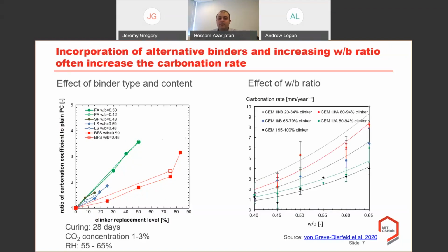The other one is the water to binder ratio, the quantity of the water compared to the quantity of the binder that we have in our mixture. One of the important effects of the carbonation is on the hardened properties of the concrete. Once the concrete is hardened, the permeability of concrete, which is affected by the water cement ratio, will result in the carbonation extent. As you can see, once we are increasing the water to binder ratio from 0.4 to 0.65, the carbonation rate will increase exponentially as a function of the water to binder ratio. And when we have a high water to binder ratio, the concrete will be more prone to carbonation, and there will be a greater depth of carbonation because of the increased permeability in the binders.